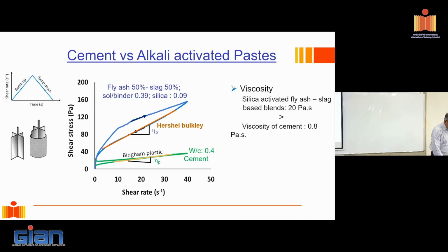But if you look at what I get for these materials, here I'm doing a slightly different test where I'm doing a ramp up and a ramp down. This was also discussed yesterday using a vane setup. So this is what you typically get for cement. You get this during the ramp up and this during the ramp down, and it's a pretty steep ramp down, and it's a very straight line. So this is a very good approximation of Bingham plastic, right? You've already seen Bingham plastic. If you look at the ramp down curve here, it's pretty straight. And if you project it back, there's a little bit of nonlinearity here, but that's something we can ignore. So when you look at cement paste doing the ramp up and ramp down experiment, it behaves like a Bingham plastic.